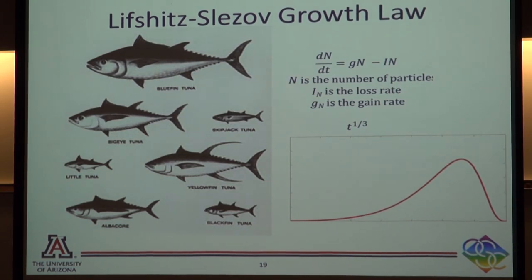So we give this indium atom all the time to wander around, to figure out what to do with itself. If you write the law of the total number of particles in a particular island, with all this time in the world, some atoms will be going away from it, and some new atoms will be sticking in. So if you write the law of gain rate minus loss rate, you will see that for the 3D structure, you have a T to one-third law.